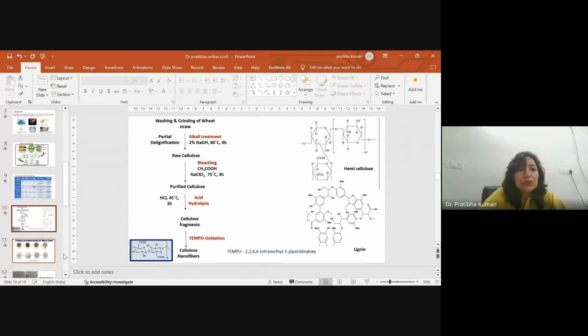Now here we used wheat straw to isolate nanocellulose. So first of all, we wash the wheat straw and we grind it. Then we treated it with alkali. We treated it with 2% NaOH. We heated it, and this leads to partial delignification because the lignin is there. So some part of the lignin gets removed when we treat it with the alkali. We'll get the raw cellulose. Then we performed bleaching by using acetic acid and sodium chlorite.